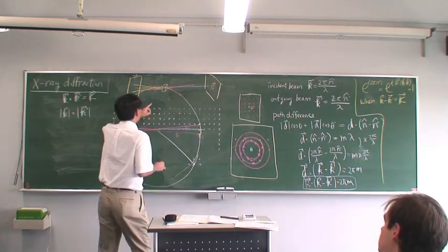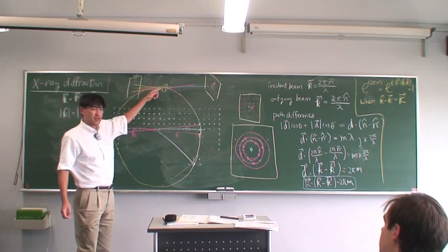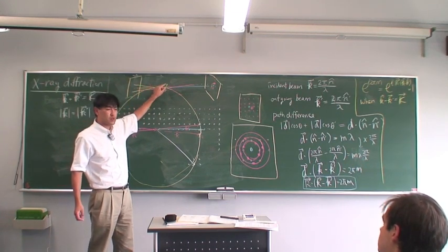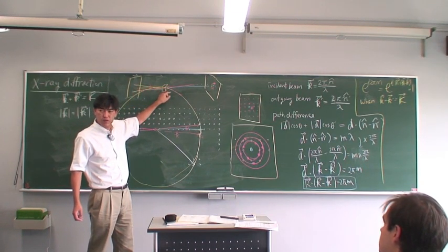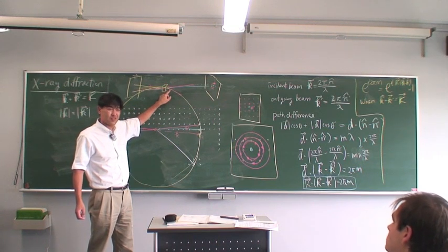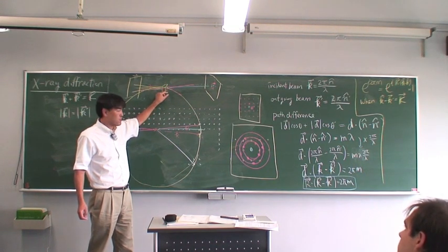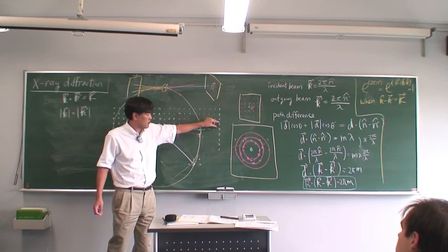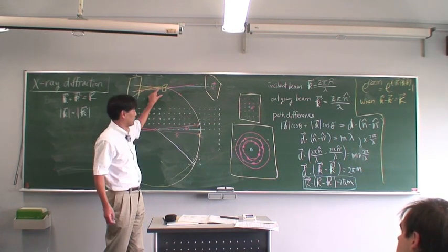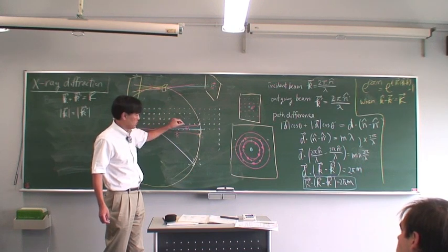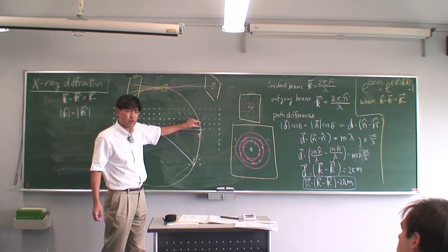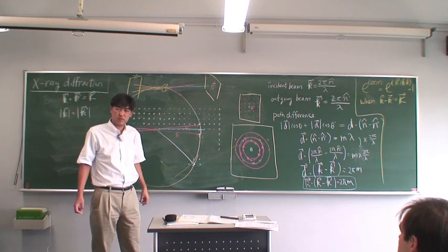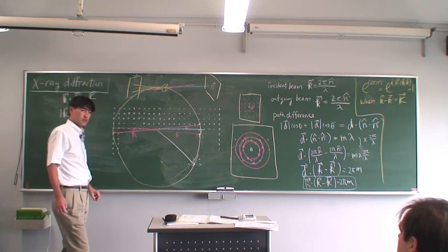So here, we are using X-ray to probe only the finite volume of the crystal. Because we're probing only a finite volume, not the infinite volume, we get a fattening of the reciprocal lattice point. Okay?